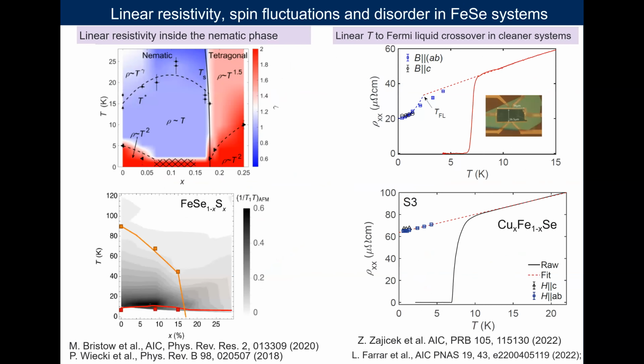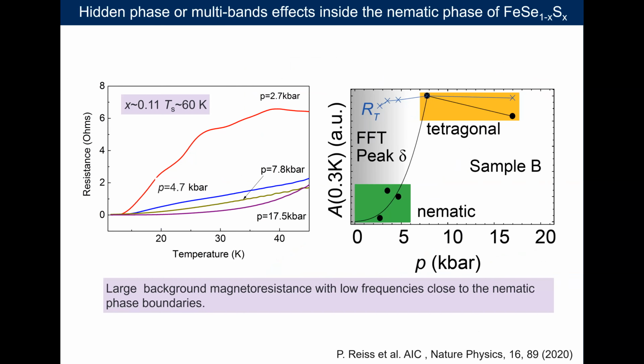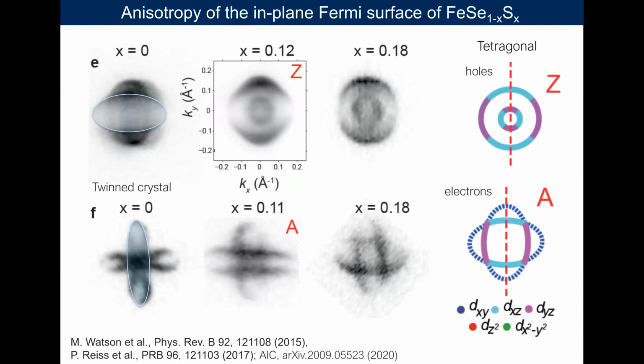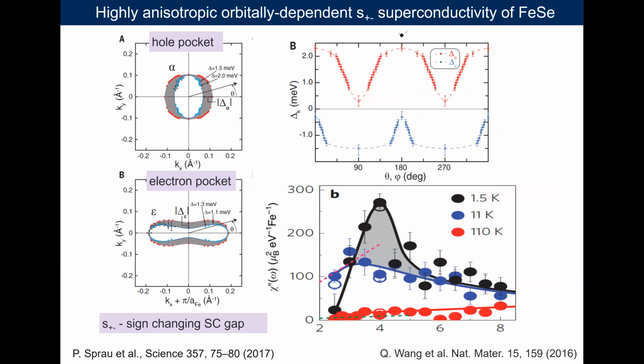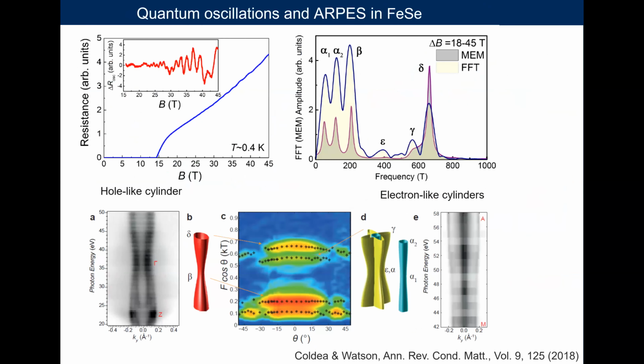So it's the development of anisotropy in the spin susceptibility of the system. So when you think why the system becomes nematic, obviously you can think, okay, you have different orbital characters. You can create changes in the occupation of different orbital characters that could give you charge or orbital order effects. But you can also have effects caused by the spin sector. So if you have spin fluctuations, those could become anisotropic and drive many of these effects.